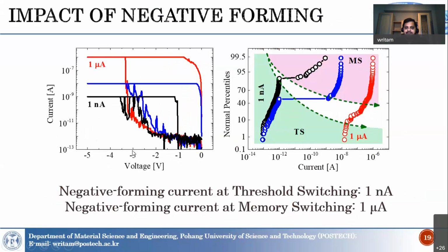Now if we have different levels of current, like from 1 nanoampere to 1 microampere, during the negative side forming process, the structure of the filament will totally change. With 1 nanoampere, or low compliance, the structure mostly shows threshold switching type behavior. But at high compliance, the oxygen vacancies will be much higher, so when you apply the positive side, there's much better injection of silver. This gives a very stable filament, but it can also go to a very low resistance state, and the device switches to memory switching.